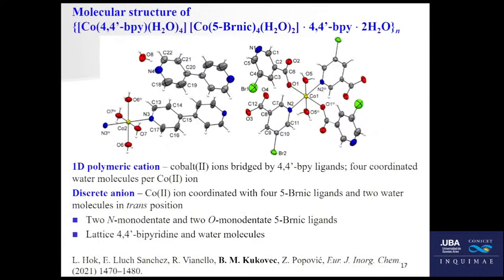The second one, obtained by using 5-bromonicotinic acid, was a bit more complex, because here we have a complex cation, a complex anion, and some lattice bipyridine and water molecules. The cation is a polymeric one. It's shown here. Cobalt ions are bridged by 4,4'-bipyridine ligands, and there are also four water molecules coordinated to a cobalt ion. So this is a cation.